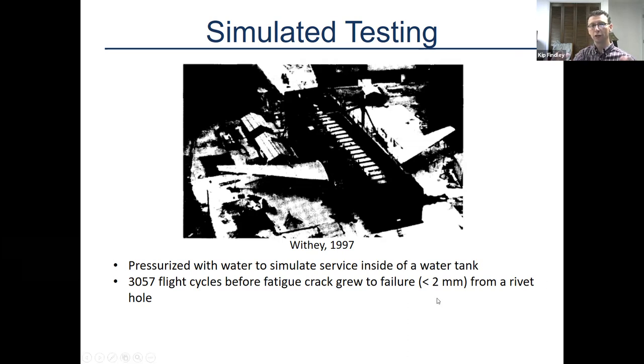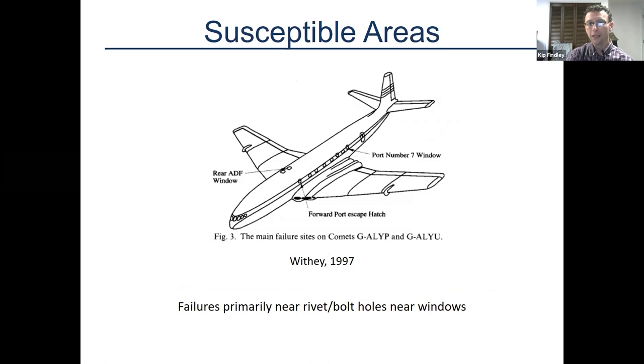Oftentimes you'll hear people say that these failures occurred around the windows, associated with the square nature of the windows, and that's not quite it. It is associated with the windows and how they had to join the material near the windows, but primarily these failures happen near rivet holes or bolt holes in the airplane. And so what they found is that there's a number of locations that are vulnerable, and again, they're all near windows. So this forward port escape hatch is one vulnerable site. There's a rear ADF window that was another vulnerable site.